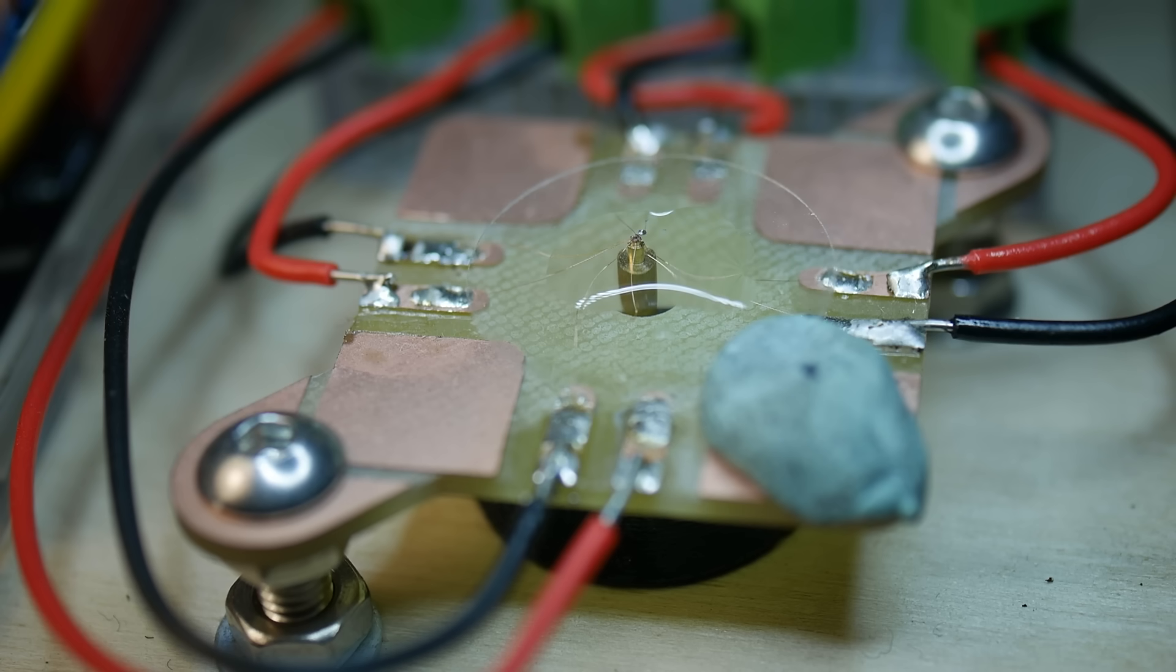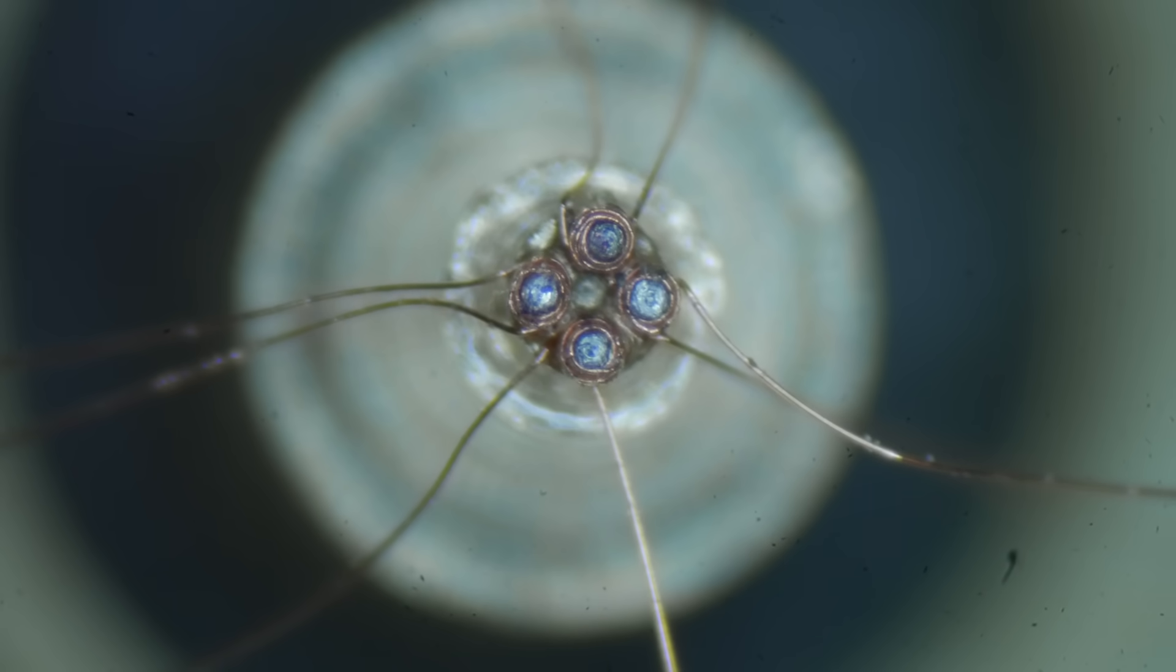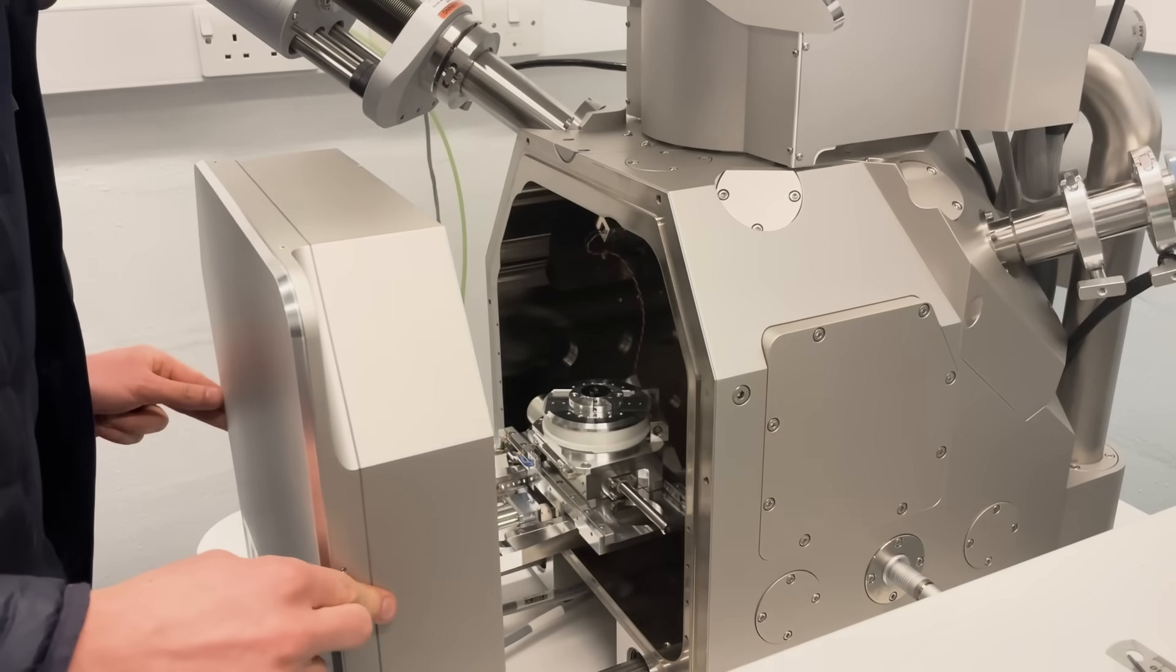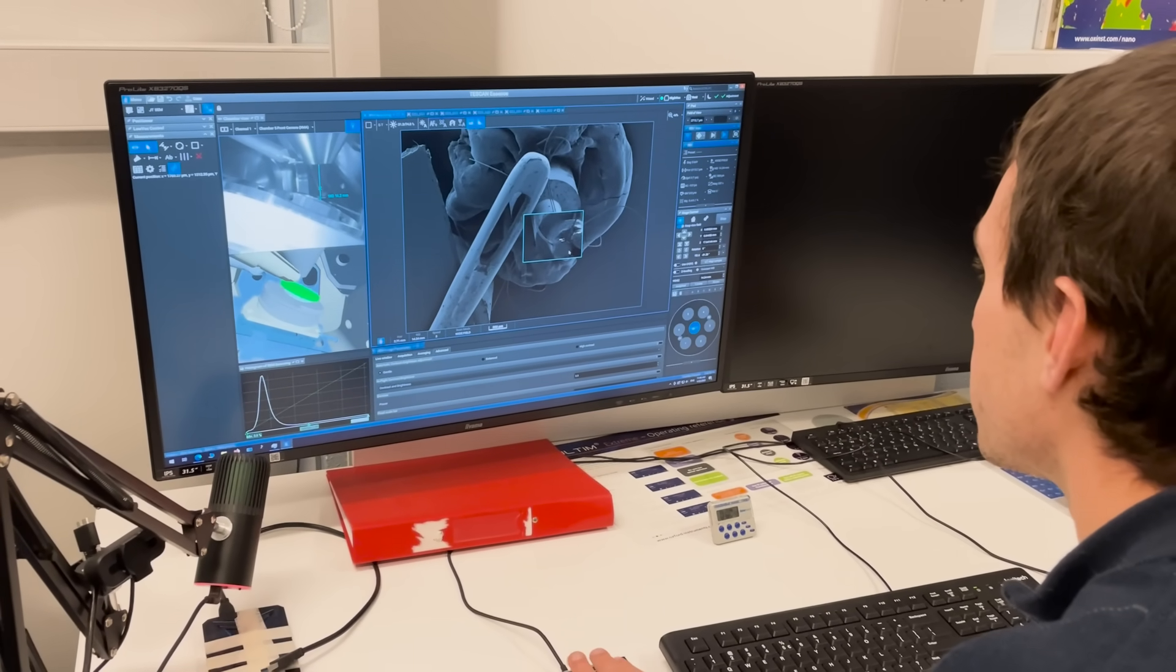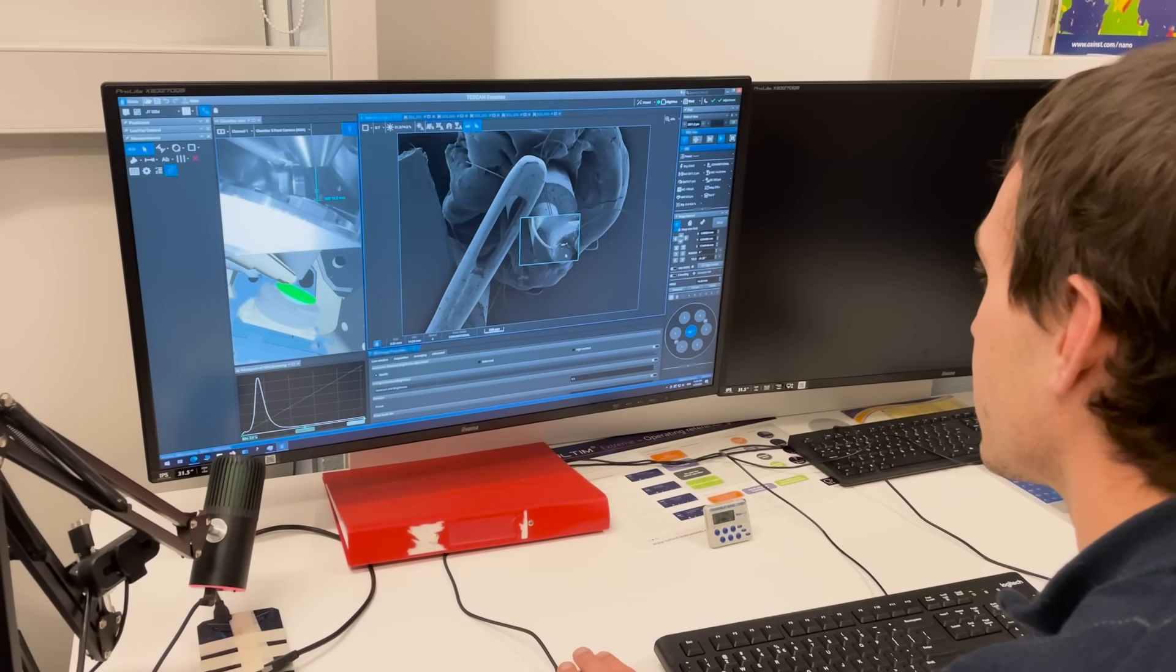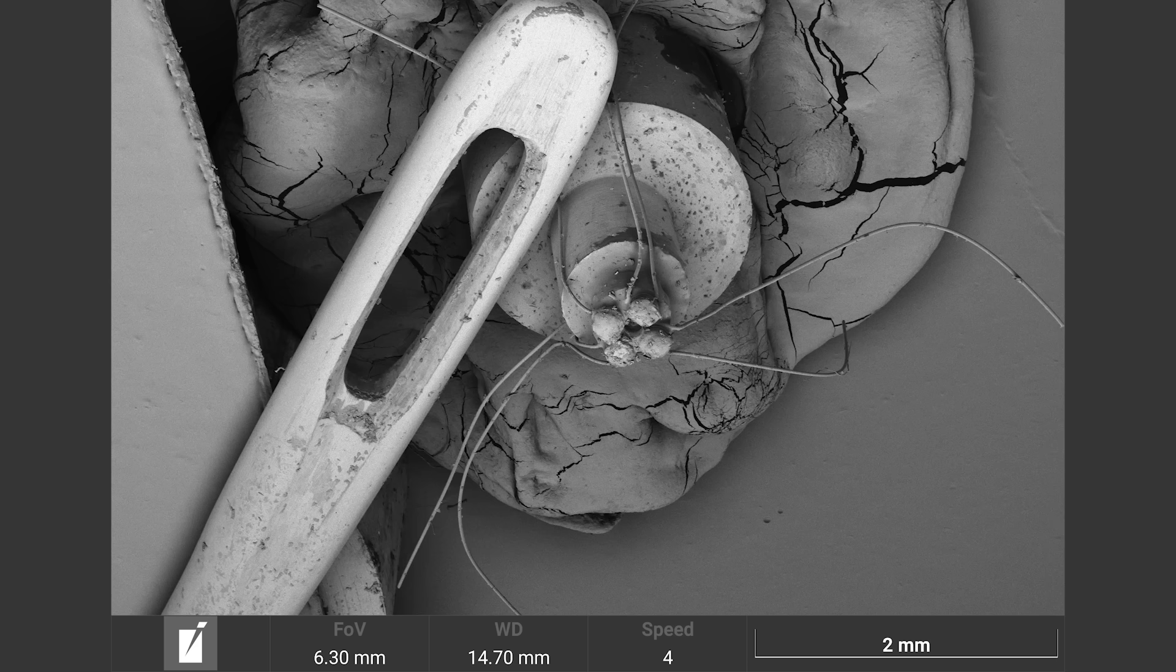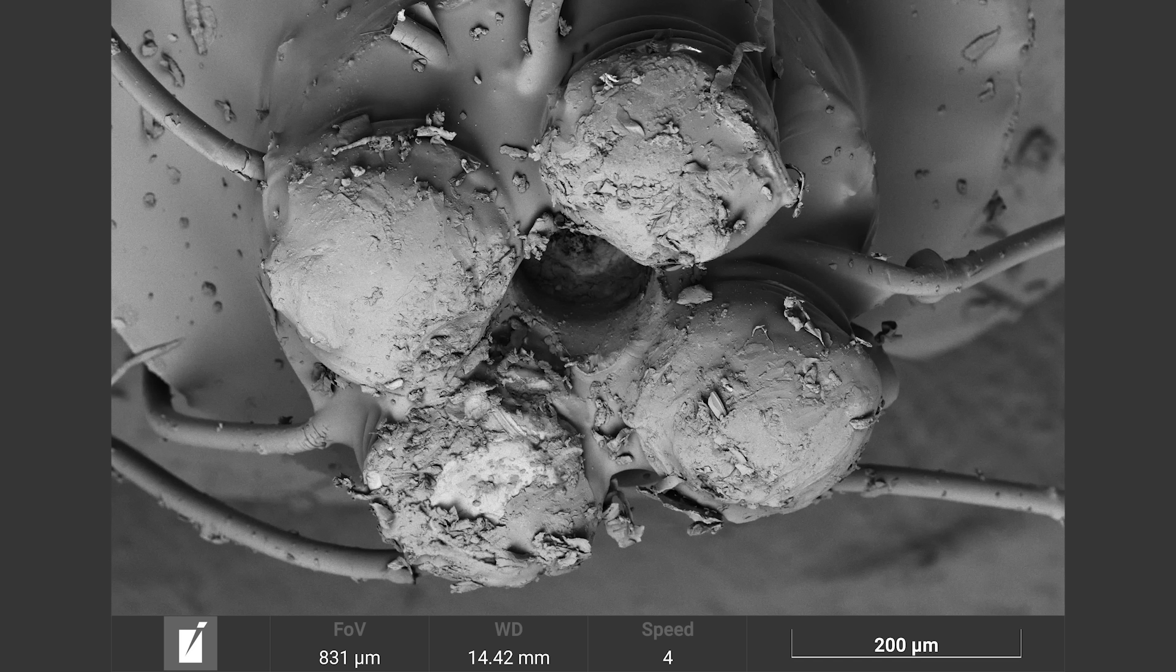Earlier in the video, I mentioned I applied cyanoacrylate to secure and protect the coils, but accidentally applied more than I intended. Under the optical microscope, it is difficult to see exactly how badly the excessive adhesive application affected the device because it's transparent at optical wavelengths. The good news is, the adhesive is opaque to electrons, which means we can use a scanning electron microscope to learn more for my next attempt. I just want to say here a special thanks to the Biomedical Imaging Unit at Southampton for kindly letting me use their microscope. Here is a scanning electron micrograph of the motor assembly next to a standard sewing needle eye for scale. You can see the coils are not very well defined because they're just engulfed by adhesive. If I zoom in, you can see the coil windings at the top, and you may also notice I accidentally broke one of the coil wires during sample prep. You can also now see all the debris generated by using a toothpick to manipulate the coils.